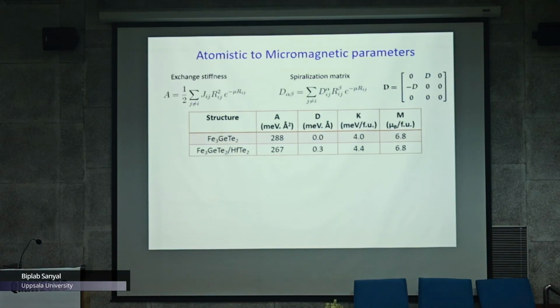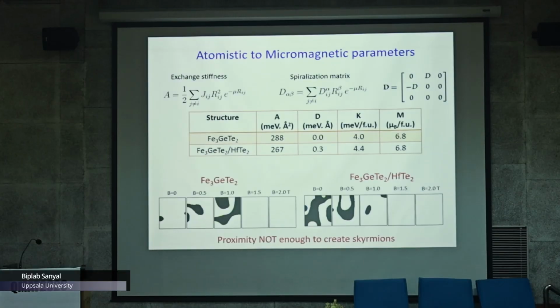For that, we do the same things, the DFT calculations, and we calculate the atomistic parameters, and then these atomistic parameters can be converted to micromagnetic parameters with this formula. Basically, you need the exchange stiffness and the D vectors coming from the Dzyaloshinskii-Moriya interaction vectors. You can take all these things, and for these two systems, they are listed here. You see the D value is completely zero for the pure iron germanium telluride system, whereas you have a certain small value here for this heterostructure. But then with all these parameters, if you do the micromagnetic simulations, you do not see any signature of skyrmions.